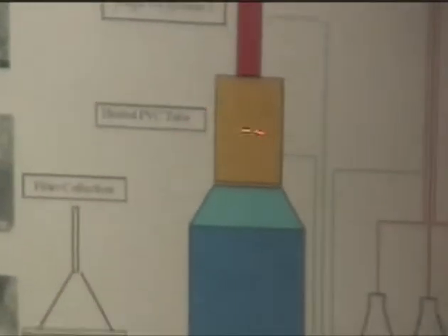When we really want to make a lot of powder, we go to this kind of mixed feed system where we run the vapors into a mixing chamber and mix them at high temperature. Then we have controlled temperatures along the route, and we collect powders down here, which are our heterogeneous catalysts for these oxidation reactions. It's basically the same slide, but this is how we've been looking at this recently.